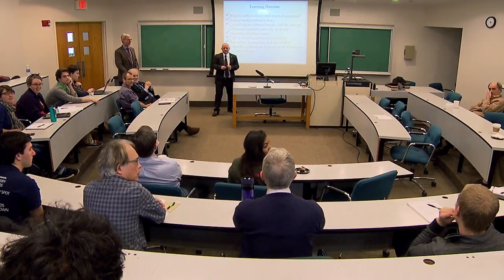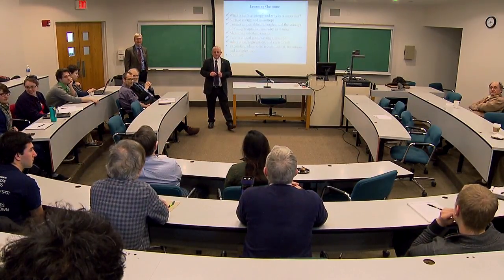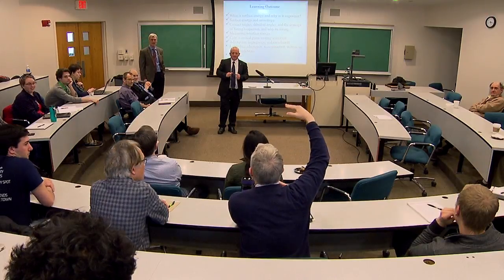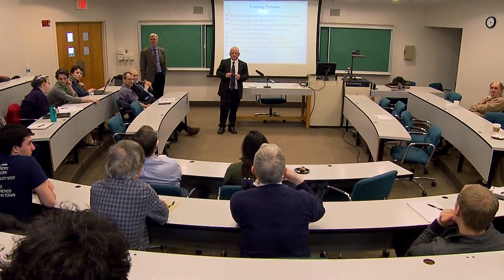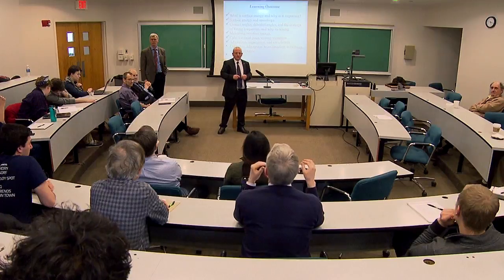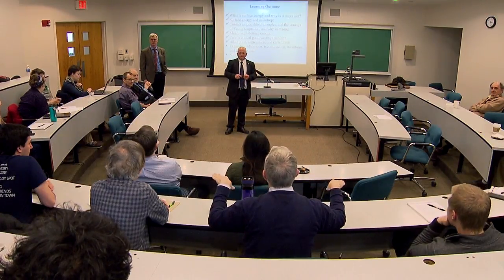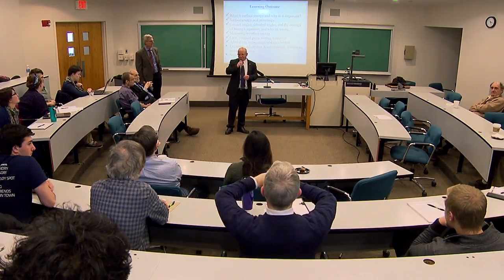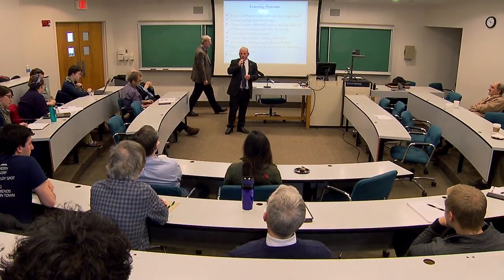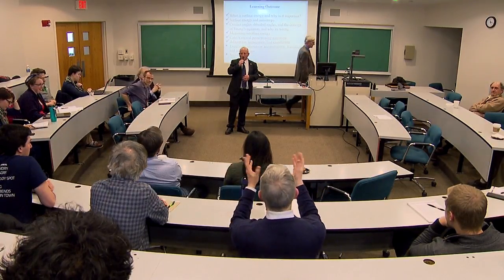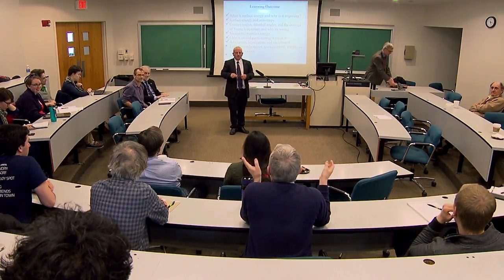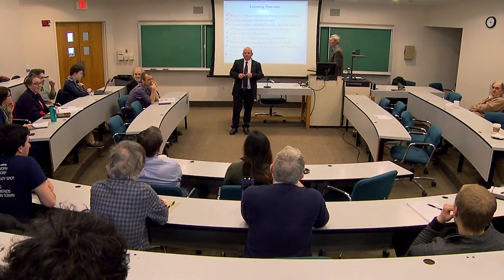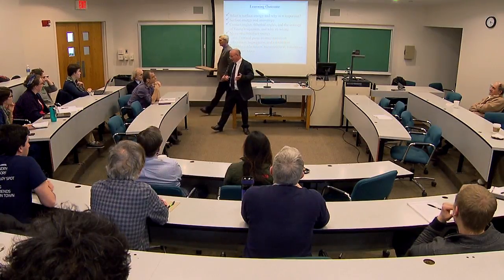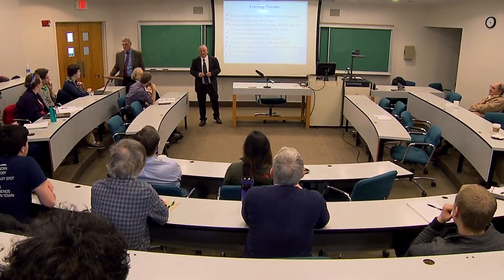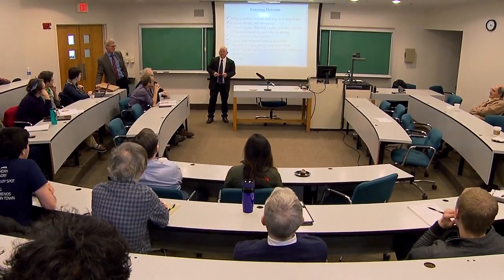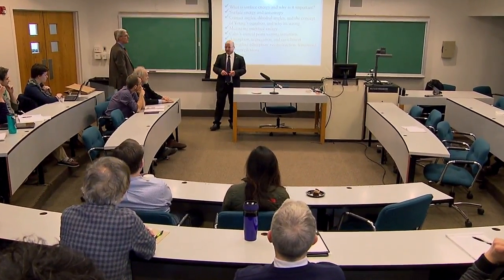Now, I was unfamiliar with Cahn's critical wetting transition, but when you get to the top of that miscibility dome, where everything is going to mix, something has to be changing between partial wetting and the point where everything just becomes one solution. This is the first time I've even heard about the concept, and it seems plausible that it could happen. By the way, they actually experimentally proved it. It's not only a calculation. It's really amazing work by Cahn and simply worthy of an amazing medallion in its own right, in my opinion.